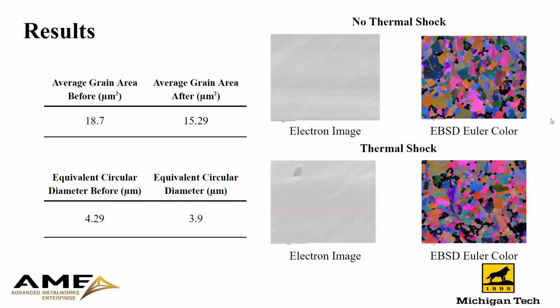Moving on to EBSD results. After the physical testing, there was the resistance change that was predicted, and we compared average grain size and equivalent circular diameter of the pre and post thermal shock wire, and there was a change that aligns with the change in resistivity.